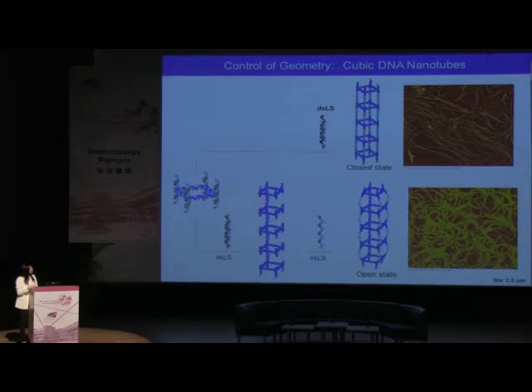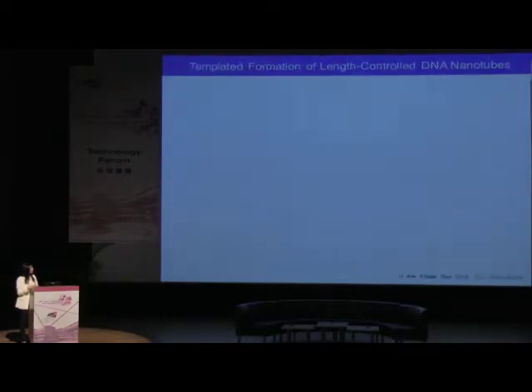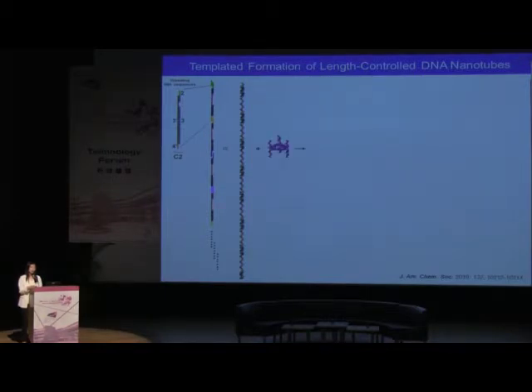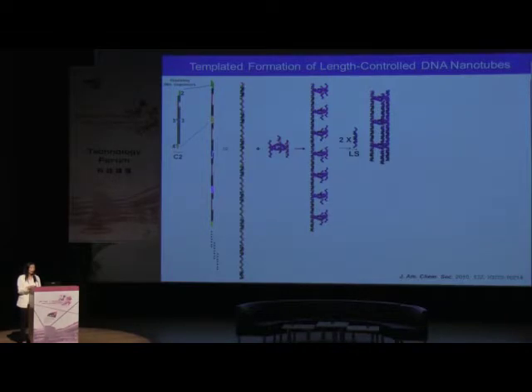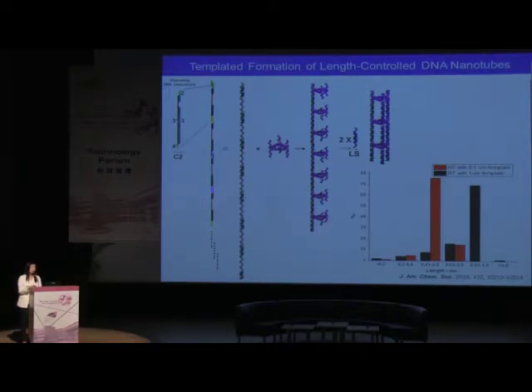So besides controlling the shape and the dimension of the nanotube, we also would like to control the length of this kind of assembly. And here we use a guiding strand approach. First of all, we take a repeating DNA sequence unit. And by only changing the sticky end sequences 2 and 4' here, we can add them one by one to form a well-defined template with the desired length. And after that, we just put in the preformed triangular rungs and close the tube. And based on the length statistical analysis, we found that we can really control or narrow down the length distribution depending on which template we are using, the 0.5 micron or 1 micron here.